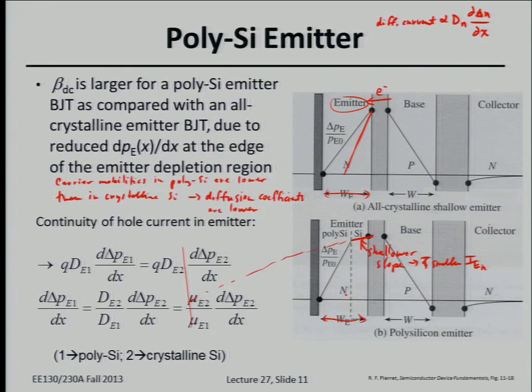So the question is, why don't we make it amorphous silicon? Okay. The mobility of electrons in heavily doped polysilicon is on the order of 50 or less, tens. In single crystalline silicon, it could be like 100. Amorphous silicon is like 1. So I guess you could make it amorphous, but practically during the fabrication process, if you deposit amorphous silicon on single crystalline silicon, because of the high temperature involved, it will naturally crystallize. And amorphous silicon having such low mobility will be more resistive, so you'll have more emitter series resistance, which